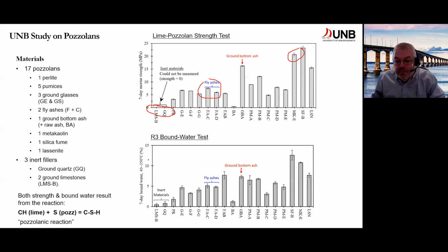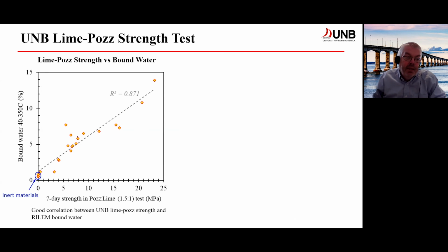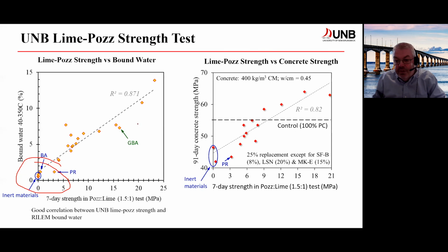So again, both of these test methods are quite capable of determining the difference in performance between reactive and non-reactive materials. And what I'm doing here is comparing the 7-day strength in our pozzolan lime test with the bound water test. You can see there's an excellent correlation. Here are the non-reactive materials down here. And you can see the general correlation is very good.